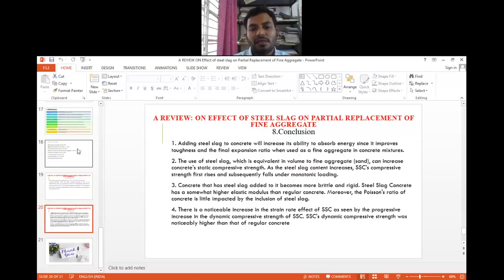Next, conclusion. Adding steel slag to concrete increases the energy absorption ability throughout the final expansion ratio. When used as an aggregate, steel slag equivalent in volume to the fine aggregate increases the static compressive strength as the steel slag content increases. The concrete with steel slag becomes more brittle and rigid. Steel slag concrete has somewhat higher elastic modulus than regular concrete. Moreover, the Poisson's ratio of concrete is also slightly impacted by including steel slag.